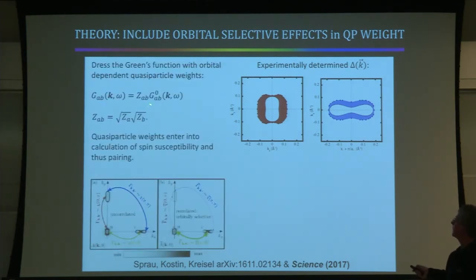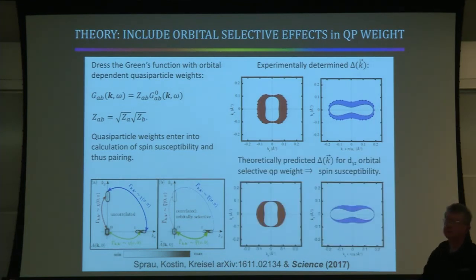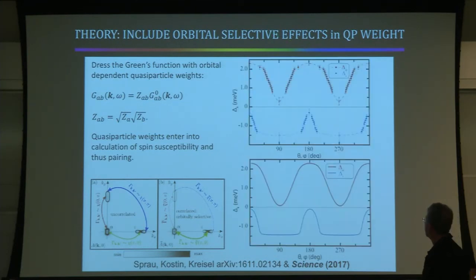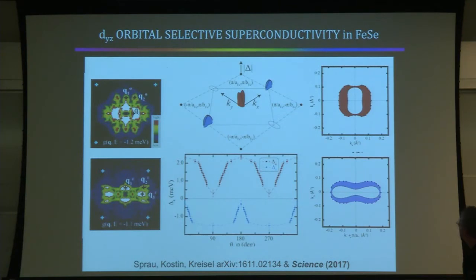However, you can do a different calculation. You can alter the spectral weight of the Green's functions according to their orbital identity, suppress the dzx orbital spectral quasi-particle weight, and retain the dyz orbital quasi-particle spectral weight, and solve another linearized gap equation. You can find a nice parameter set which will give a gap structure very quantitatively as observed. Okay. So here we are. We believe this is direct evidence for orbital selective superconductivity in this compound. And it's the dyz orbitals on the iron atom which form the Cooper pairs. dxy and dzx are doing something different. So this will be reported now in Science in a week or two.